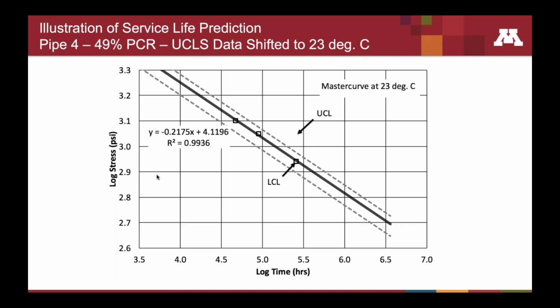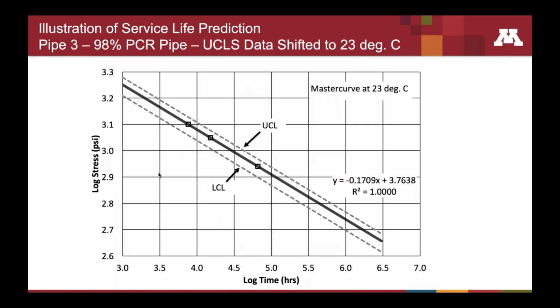Then we can go back to these service life projection curves, and instead of projecting our failure time at 500 psi stress, we can go to that stress level, and we can create a failure window as to when that pipe would be expected to fail in the field due to brittle cracking. And so the 49% post-consumer recycled pipe would fail in a relatively short time, 1.4 to 3.2 years, still a little bit longer than was desirable for the purposes of our project.